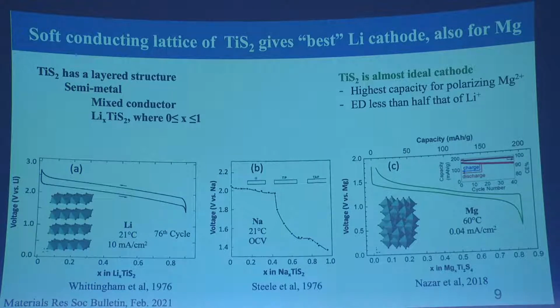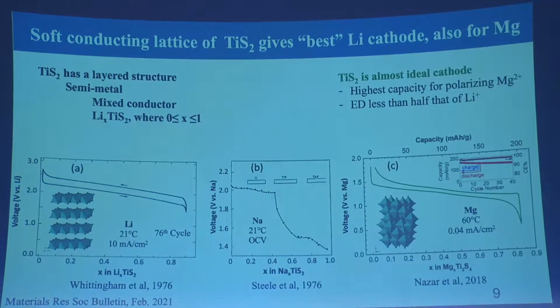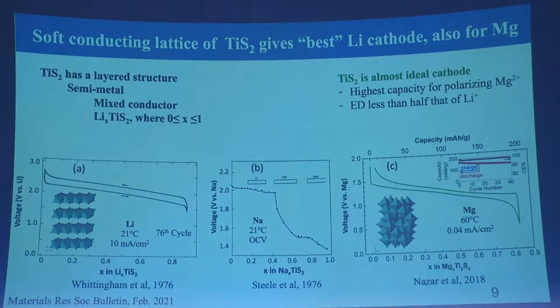So why is titanium disulfide so interesting? First, from anybody who does phase diagrams, it's a single phase all the way from 0 lithium to 1 lithium. The lithium can go in there, just slowly expands it. So you don't have to nucleate a new phase. Second, it's a metallic conductor. And the physicists here will grumble, it's really a semi-metal as they describe it. For all practical purposes, it's a metallic conductor.